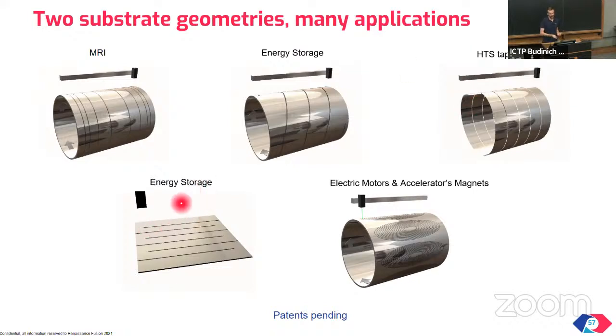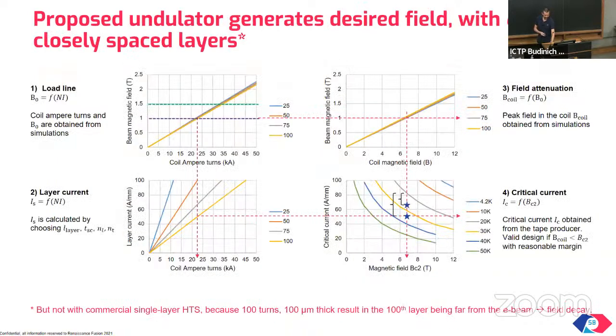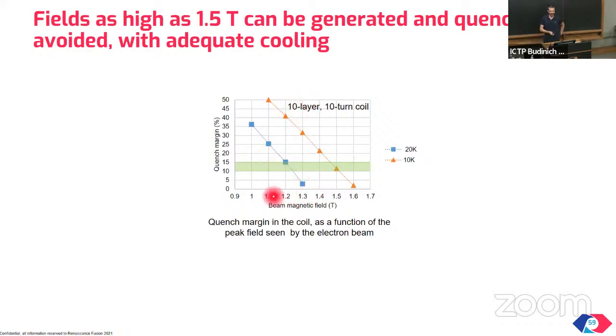In particular, we are excited about taking plates and patterning them with serpentines, as shown on the left, which coincidentally is also an energy storage concept. So when a colleague from the synchrotron saw that, he said, "Oh, that's an undulator." So for wigglers, sorry, it's an undulator for synchrotrons. I will not go into too many details because I'm nearly done with my time. It turns out that only with this technology, you can generate very strong fields on short distances. Typically, these two things are mutually exclusive, but in a good undulator, you want to aggressively bend the trajectories of your electrons, but for reasons of coherent sum of your X-ray signal, you want to sum up over several periods. Therefore, for the same total distance, you want many short periods. Long story short, with our technology, this is possible.